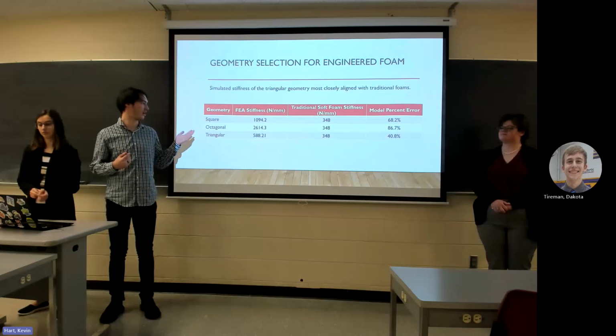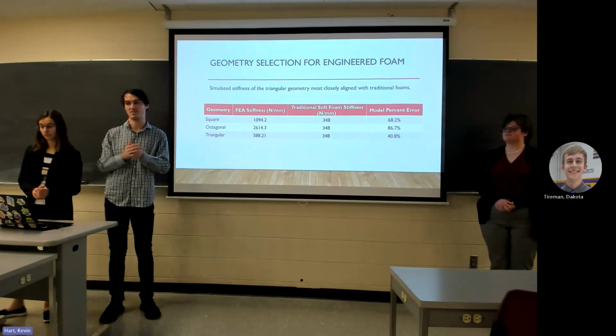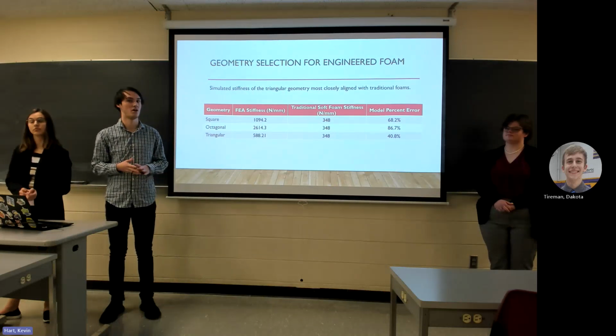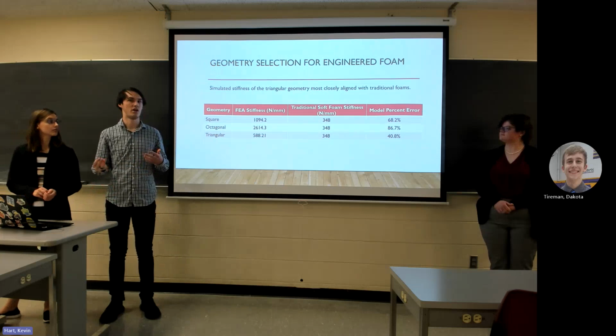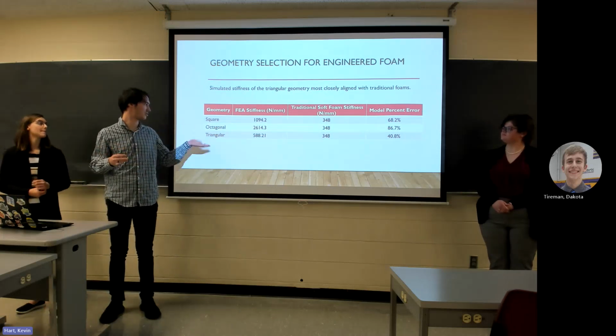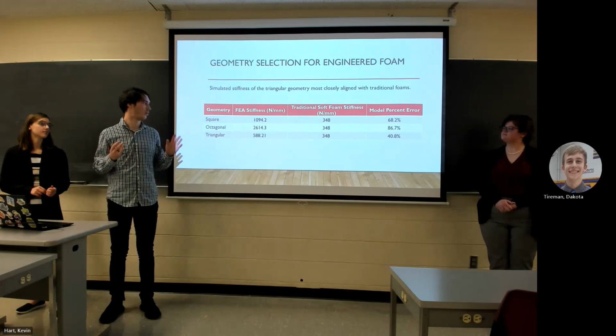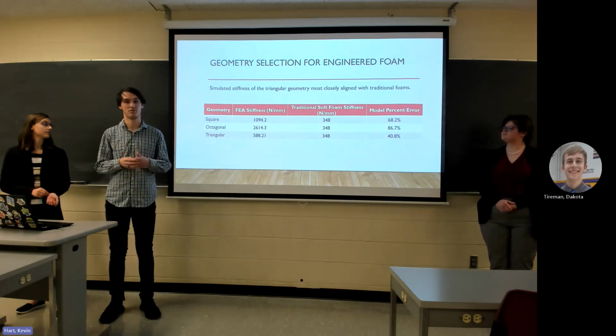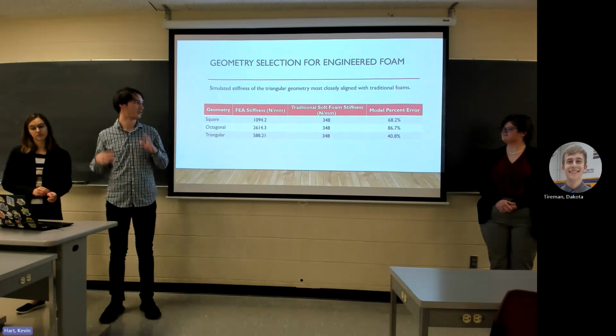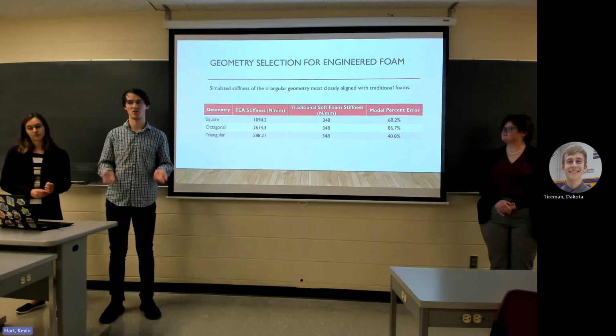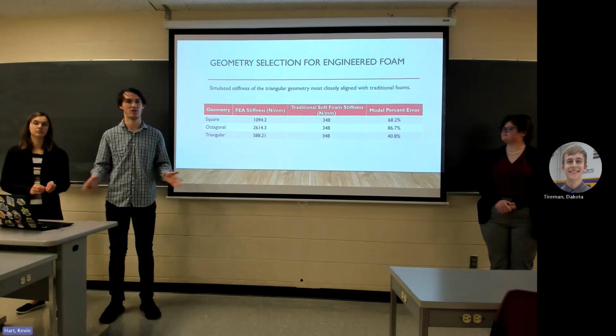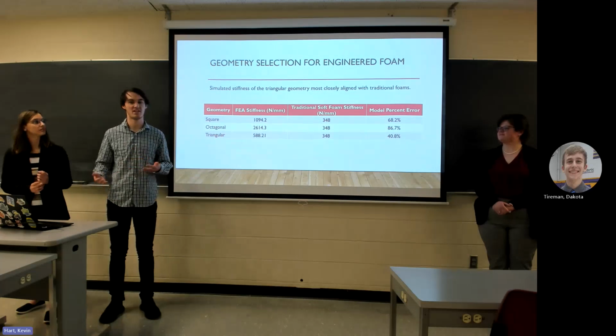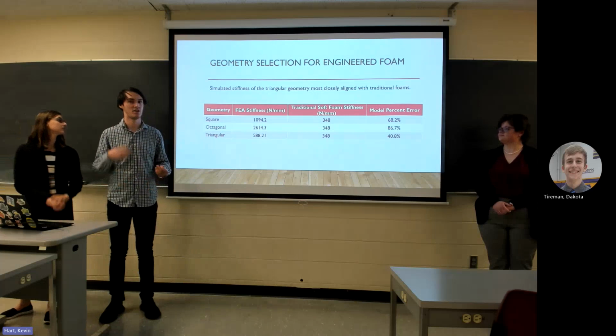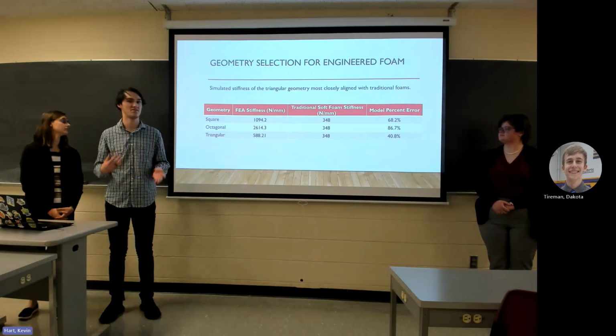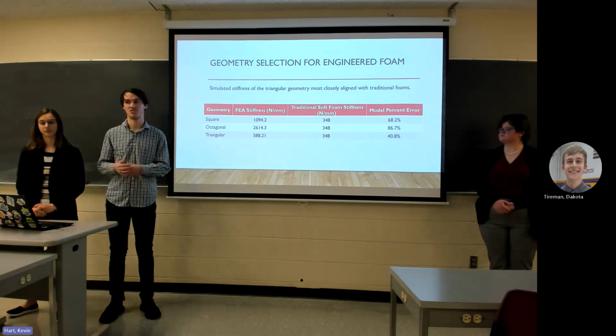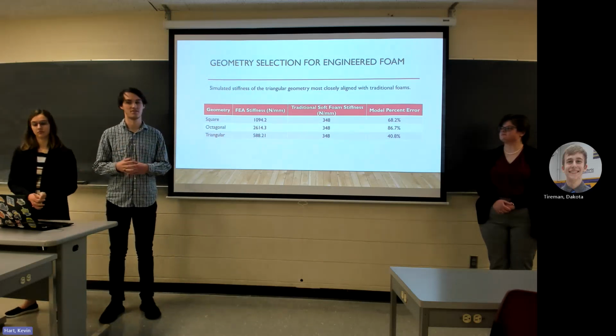So here we've got the octagonal geometry first. That's the one that's in our first iteration of the foam. That's the stiffest one. And then a step down from that is the square geometry, which is less stiff, but still very far off. The hexagonal geometry, when we tried to run the FEA on it, it just completely exploded and blew up. But since we knew from previous testing that in general, the hexagonal geometry is close to the same stiffness as the square geometry, we knew it probably also was not going to be able to work for this foam.